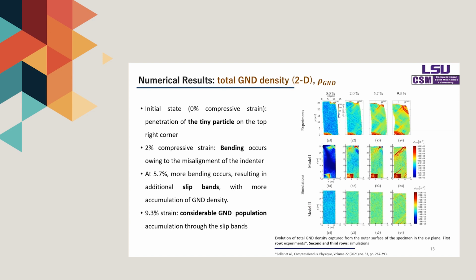Bending mode is observed at 2% compressive strain due to the misalignment of the indenter. At 5.7% compressive strain, additional slip bands are initiated.